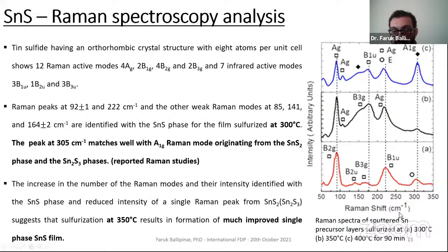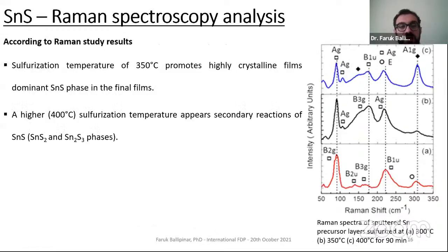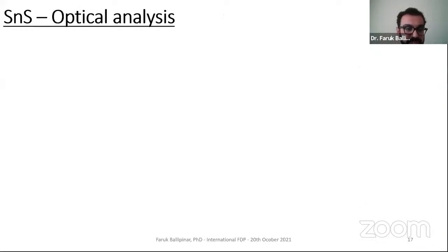Looking at our Raman spectra analysis, the peak started to occur around 300 Raman shift in the 400 degree sample. So basically, Raman and XRD results match very well. The 350 promotes highly crystalline and dominant tin sulfide, but the higher temperature, 400 degree, shows secondary phases, kind of mixed phases, both SnS, SnS2, Sn2S3.